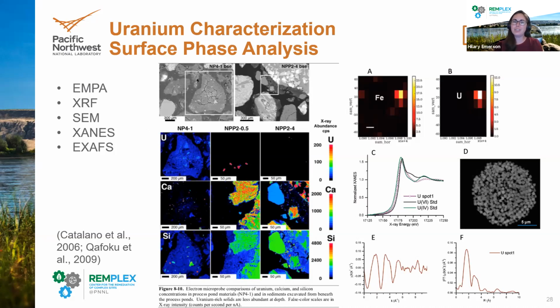And this is an image from Nick Qafoku's previous work that shows an iron pyrite phase that was bioreduced and incorporated uranium. And they were actually able to use some beamline techniques, including X-ray absorption near edge structure and extended X-ray absorption fine structure to probe the oxidation state and coordination of uranium to confirm that it was incorporated into that phase as a uranium-4 species.